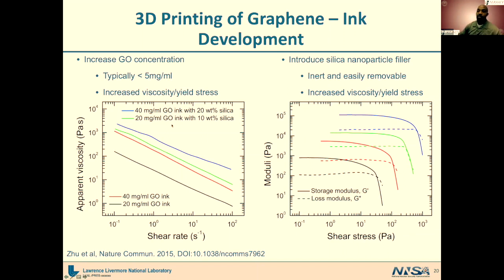So we go about achieving that by, one, increasing the concentration of graphene oxide, or these nano sheets, within our suspension. We also add in some fumed silica, which are these silica nanoparticles. And currently we're also working with other modifiers as well, such as various polymers and carbon-based viscosifying agents. You also want to have a fairly good yield stress. By increasing the GO concentration as well as these viscosifying agents, we're able to increase both the viscosity and get to a high enough yield stress such that we can print the ink.